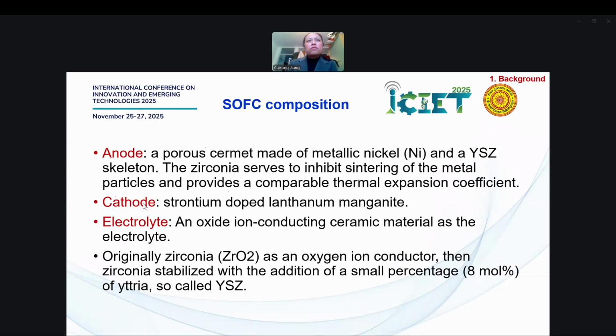Now think about how fuel cells work. We need three components: the first is the anode, the second is the cathode, and the third is the electrolyte. The anode could be a porous cermet made with metallic nickel and YSZ as a mixture. The YSZ inhibits the sintering of the metal particles, prevents thermal expansion mismatch, and gives oxygen ion conductivity, and nickel gives electron conductivity. So that is how it works for the anode.